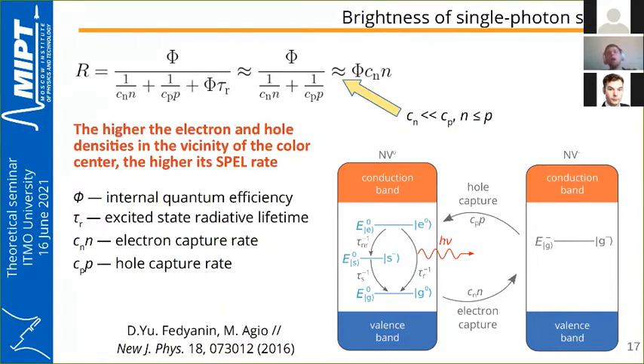In the case of diamond, the electron and hole capture rates are very low, so we can neglect this term, the excited state radiative lifetime, and obtain the following expression. Also, as I already said, we have some inequalities with Cn and Cp, which eventually allow us to simplify the expression to just quantum efficiency times Cn times n.